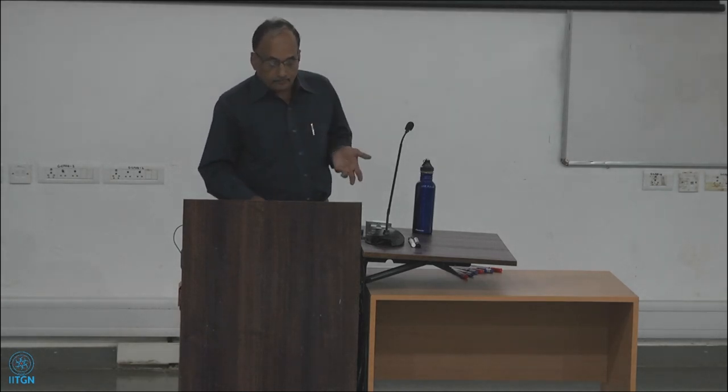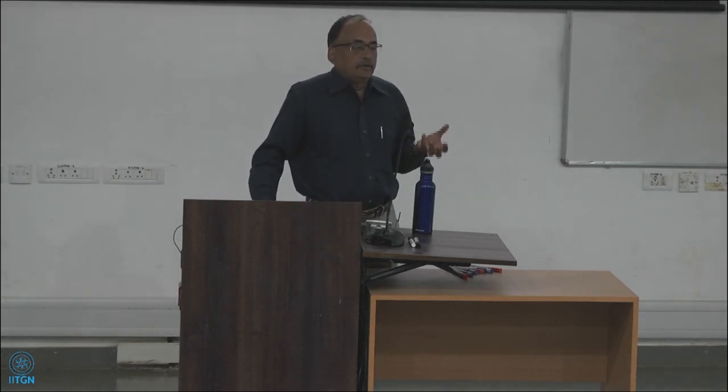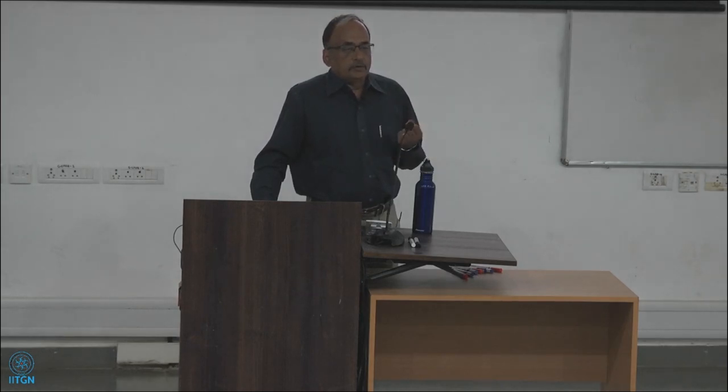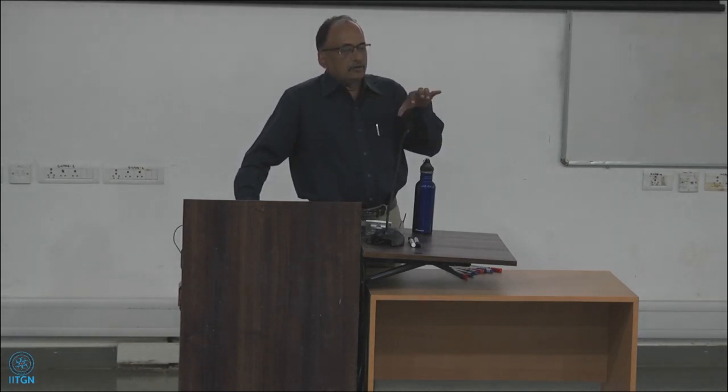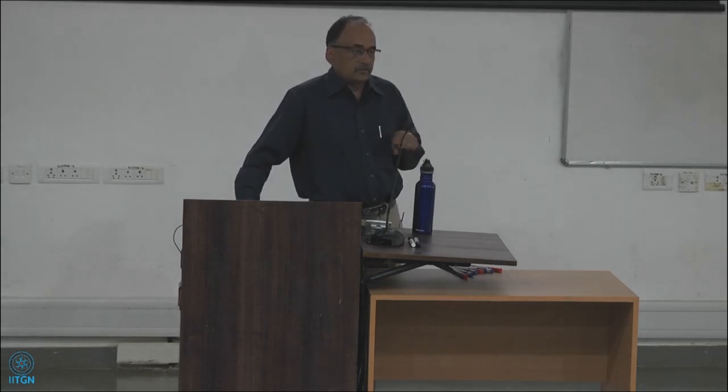This is the stratigraphic distribution that I mentioned. Then also functional difference. For example, if you look at the cooking vessels, you will find a domination of plagioclase feldspar and calcite. These are the minerals that you generally find in cooking vessels. It may have started as an accident, I don't know. But the interesting part is that the coefficient of expansion of clay and the coefficient of expansion of these minerals are very close to each other. So when the cooking vessels are continuously heated, 3 or 4 or 5 times, they do not undergo any kind of shear or stress and do not break. They get a long durability because these kinds of minerals are used. Calcite is also one of them.